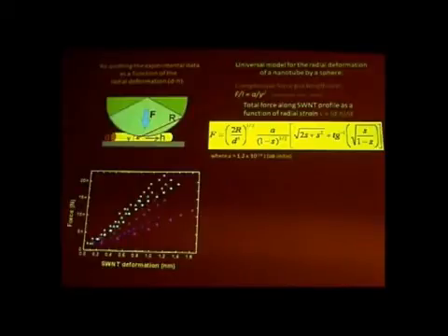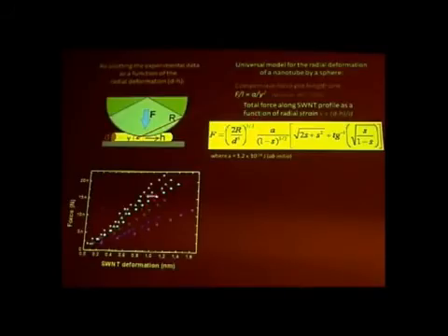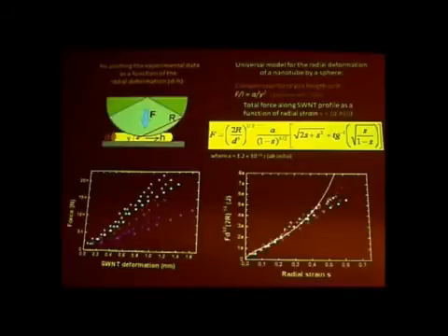We came up with this equation, which says that for all the nanotubes, this part of the equation is dependent only on the strain, which should be universal for any nanotube. So if you rescale our graph here with this constant, then all nanotubes should have the same behavior. And indeed, we can collapse all nanotubes onto a single behavior. In yellow is our theory with no adjustable parameters, and the theory describes the experiment very well.